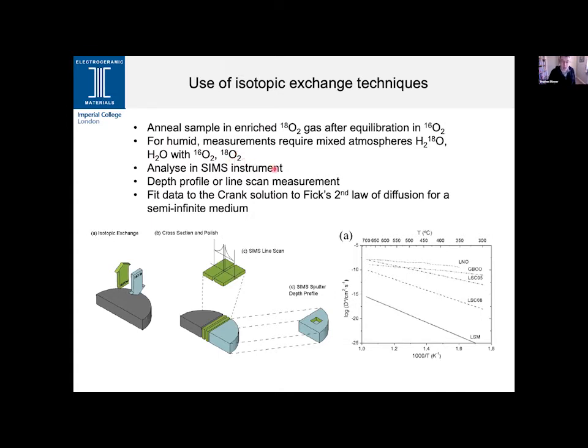We then undertake our exchange anneal, analyze the results of those depth profiles in our secondary ion mass spectrometry instrument, using depth profiling and line scanning to probe directly the oxygen transport, fitting that data to Fick's second law of diffusion. And so the process is essentially taking our ceramic, doing this exchange as isotopic anneal, and undertaking a cross section, so preparing the ceramic, polishing, making a nice section that we can analyze, creating a destructive depth profile from which we can then extract our exchange parameters, our diffusivity and our surface exchange coefficients.